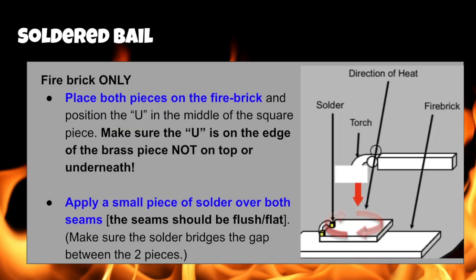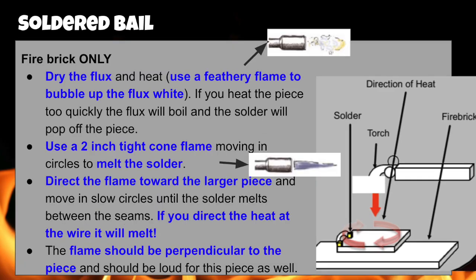Take the flux brush, pick up 2 pieces of solder and place them with the tweezers where the connections are. I would again suggest drying the flux until it bubbles up so the pieces do not move. Then you're going to change the flame to a 2-inch cone flame and heat the piece perpendicularly with the torch, focusing most of the heat on the square and moving in concentric circles until the solder melts.